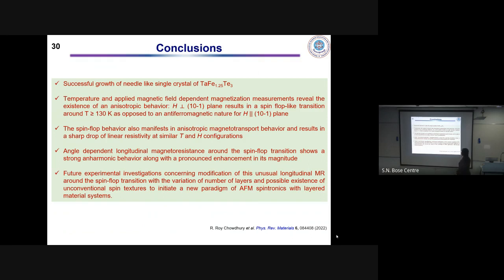Angle-dependent longitudinal magnetoresistance around the spin-flop transition shows a strong anharmonic behavior along with a pronounced enhancement in its magnitude. So what we need is basically future experimental investigations concerning modification of this unusual longitudinal MR around the spin-flop transition with the variation of the number of layers, because we are seeing the interlayer coupling is also playing a role. So it is important to perform the experiment by changing the number of layers, and we can possibly look out for any existence of non-trivial configurations in this system, which might initiate a new shift in the field of antiferromagnetic spintronics with layered material systems.